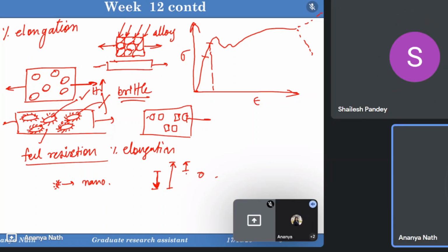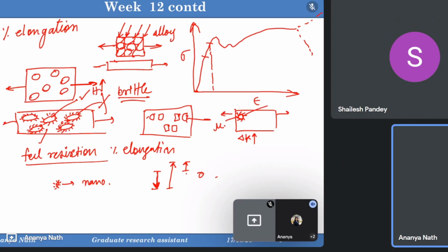I'm not saying so. Actually, if the matrix has particles in micron dimension, then if you are going for elongation, it will feel a lot of stress intensity, due to which del K, the stress intensity factor, will be very high, and it cannot get elongated, because these are brittle particles. So there can be breakage in the particles, or the matrix can simply fail.